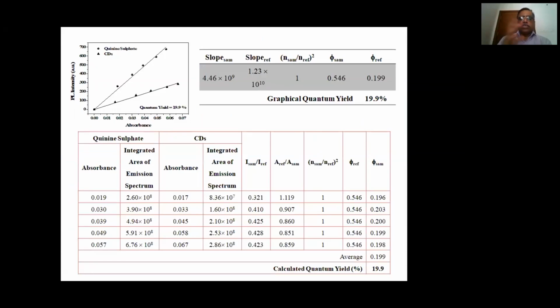Mostly carbon dots are heterogeneous and excitation wavelength dependent, and they also show multi-exponential behavior. So now you can see that the quantum efficiency is also higher in this case - quantum efficiency is almost 20% for these quantum dots.